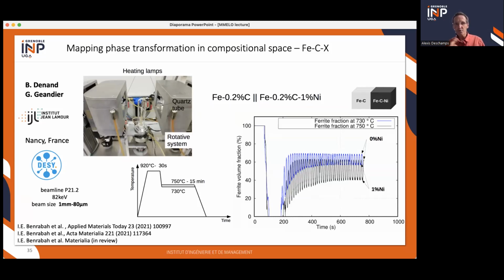And so the rotation is continuous. And then to probe the composition gradient, you just have to scan vertically your sample in front of the X-ray beam. And then you can probe the full composition gradient. And during isothermal intercritical annealing, then you can follow the fraction of phases.